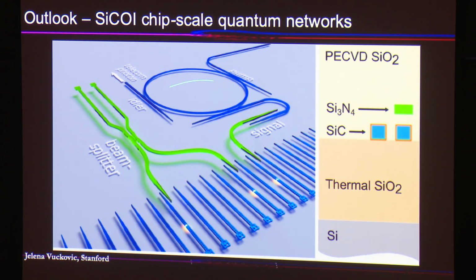But we can always make the bottom layer, find where the good qubits are, then deposit oxide, and then deposit something like nitride on top, and use that reconfiguration layer to connect the good qubits underneath. And if you are looking into atomic physics experiments, they also have reconfiguration capability, right? When they trap atoms, you never really have a perfect lattice. So then they use something like optical tweezers to reconfigure the lattice, to fill up the empty spots. And you need to do the same in photonics.